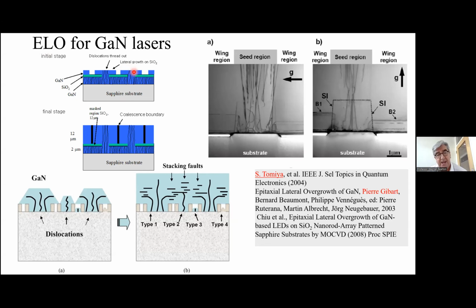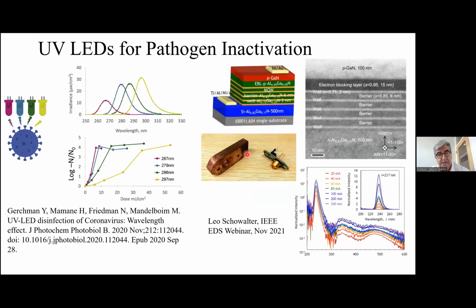So that's going to have a high dislocation density. The material that grows over the mask and eventually coalesces to form a boundary there will be highly defective as well. But in between those regions, you have regions of low dislocation density, and that's where you make your laser. So you can see TEM images here of being able to have regions on the wings of those mask regions that enable you to make low dislocation regions for lasers.